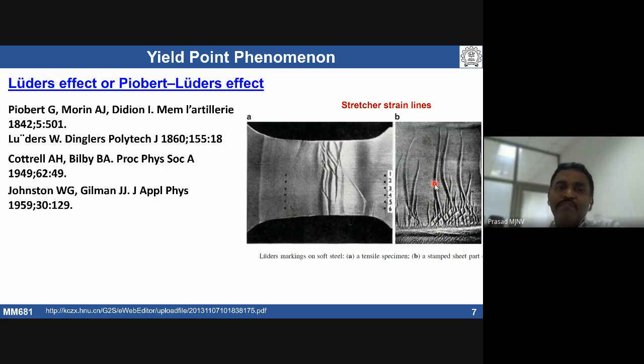This observation started way back in 1842. These were the first people who reported the formation of this stress drop and serrations. The formation of these lines was reported by Lüders, who was the one who saw this in a well-polished sample when he tested the material, observing the formation of Lüders bands, where a band forms and propagates. This was reported by Lüders in the year 1860.